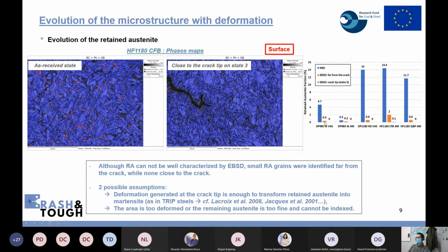and this is what is represented on this graph, with the orange value being the EBSD far from the crack, and the gray one the austenite close to the crack. And so we see that close to the crack, whatever the sample, we have no austenite anymore. We can also see the difference between EBSD and XRD, in which we see that EBSD is not the most suitable technique to characterize the austenite, because it is too thin. And so what we say here is that the deformation induced by the crack has transformed the austenite into martensite by TRIP effects. We can say that by the comparison.